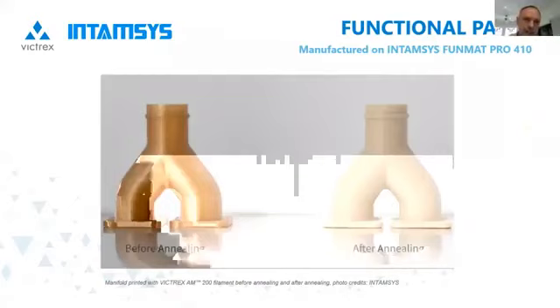So Victrex AM200 can be printed amorphous or crystalline, and it depends on the specifications of your printer and your process settings. On the left-hand side is an example of a manifold with amorphous AM200. And as I showed on the previous slide, the properties are still pretty impressive. And you can see the part here with this really nice honey color. On the right-hand side is a semi-crystalline version of the part, which improves properties such as the chemical resistance, the fatigue resistance, and the temperature resistance, especially above 150 degrees C. So it really depends where the part will be used.